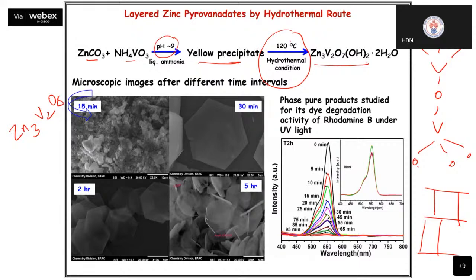Then I tried to see what difference it would have on the morphology of my product if I heat it for different durations in my autoclave. So I did that experiment. This was after autoclaving it for 15 minutes. Some product I got, some morphology. Let me tell you, for all four of them, the XRD was perfectly similar.